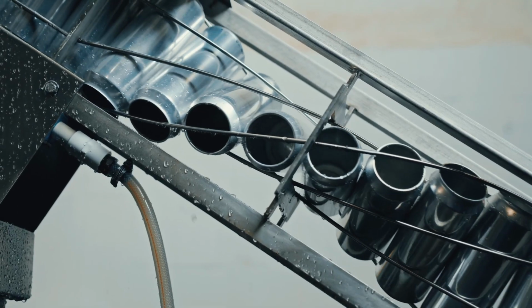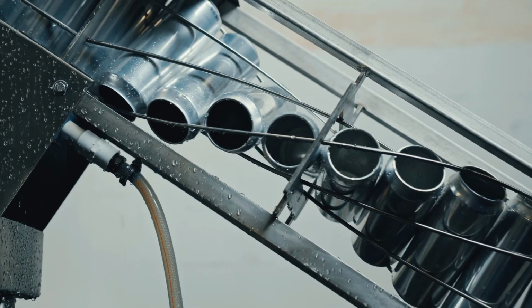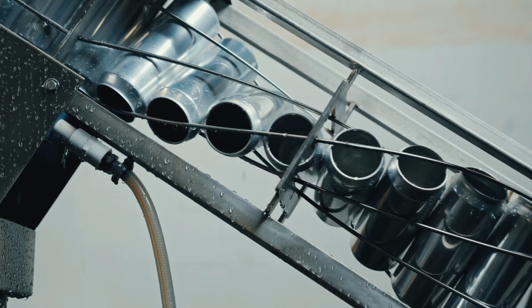Packaging manufacturers then cut 140 millimeter blank circles out of the sheet and then put them through a series of pressing operations to construct a cup 66 millimeters in diameter. To produce an even edge, the top 6mm of these cups is sliced off and scrapped. A significant amount of scrap is generated through these procedures, which are sent to remelting facilities to produce new ingots.